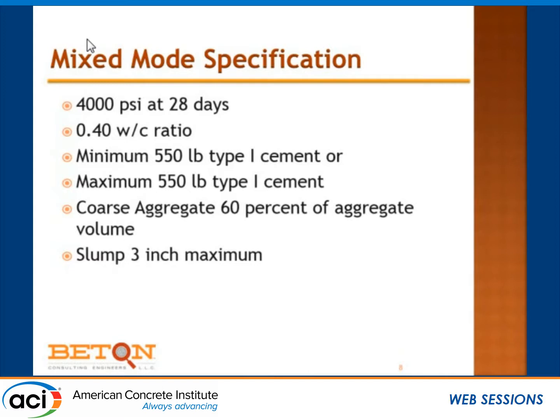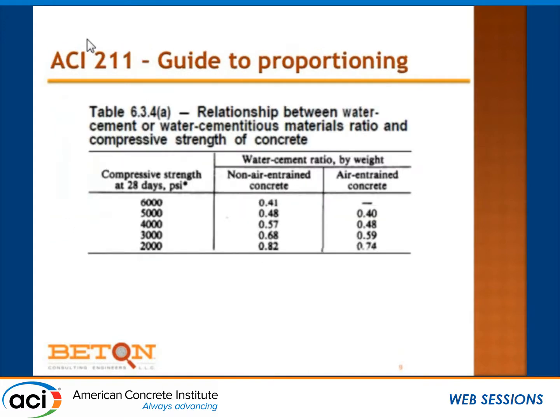We can have a minimum cement type specification, and we also see a maximum cement type specification. I have an "or" in here, although there are often "ands" that say the cement content shall be 550 pounds, which is a minimum and a maximum. The coarse aggregate will be 60% of the aggregate volume, and I want a 3-inch slump maximum. And so let's take a look at where some of these things start to give us some headaches.